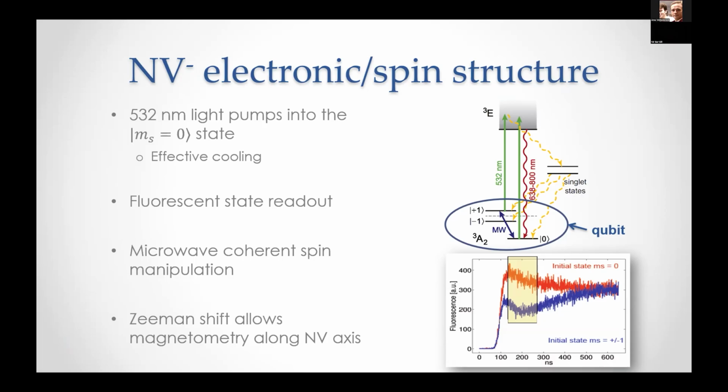Now, this phonon transition is realized through spin-orbit coupling. The spin-orbit coupling is associated with orbital degrees of freedom that are then coupled to phonons, and they create this relaxation path. Now, for a very non-trivial reason, it's very difficult to calculate from first principles, but this coupling is significant for the plus minus 1 spin states, but not so for 0.